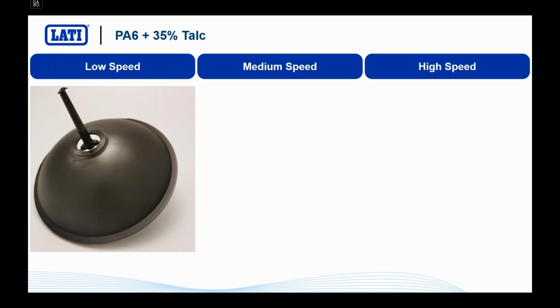If we apply a 3-gate submarine injection system, you will see that the surface is always dull, so you have always a very opaque surface, but you see that around the injection location there is something different popping up. There is some kind of spots, something that you have not seen before. You have some kind of lighter areas, and you see the weld lines. You see those lighter, more glossy surfaces evidenced by the small lens. That's a weld line.